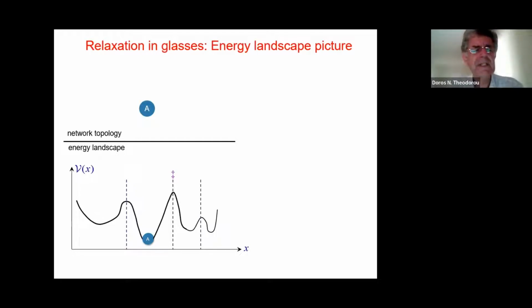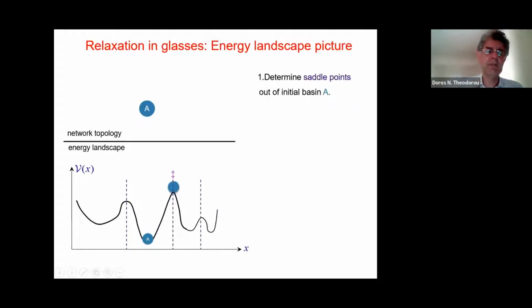Now, could we possibly address this phenomenon of physical aging that we mentioned, the fact that a glass gradually changes its properties with time? In order to do that, we need to probe transitions from one basin into another one. And that is quite a bold and ambitious goal, of course. But what we try to do is we start from a basin, we start from a local minimum, and we try to calculate as many as possible saddle points around this minimum in the multidimensional configuration space of the glass.